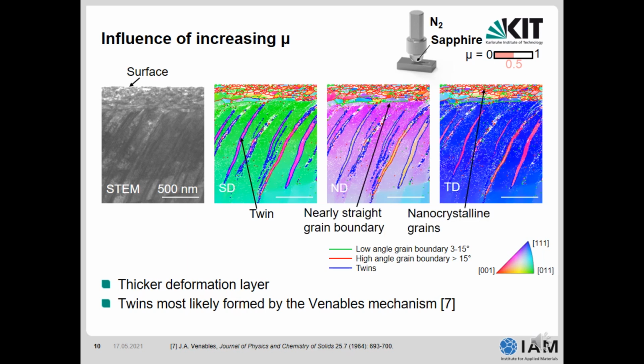So then we see also a nearly straight grain boundary, and above that you can see the elongated subgrains, which were also published by Hughes and Hansen. Directly below the surface you can see some nanocrystalline grains. So here we have now also two zones, one which is dislocation mediated, and in the other zone we can see twin-induced plasticity.